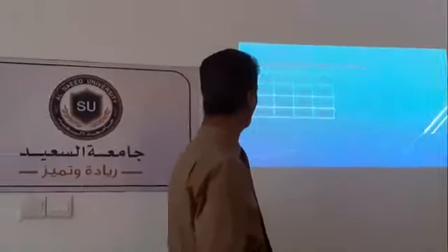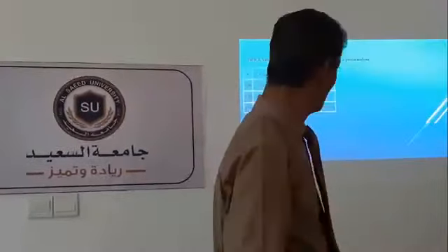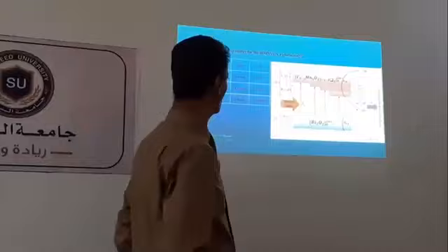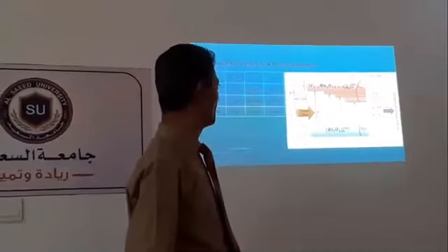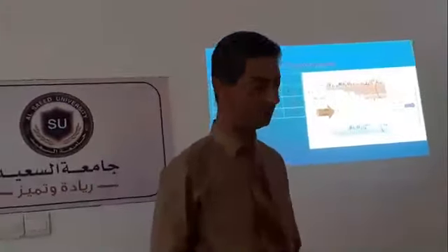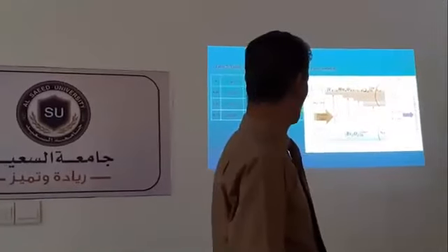Here we summarize the calculated values of band gap energy for these compositions, along with the acceptable standard deviation and correlation factors. We can see this decrease in the band gap energy with increasing doping concentration is attributed to, or can be explained by, the additional contribution of the 3d orbital of manganese to the conduction band with increasing doping concentration, as well as the increasing doping concentration in the perovskite layer.